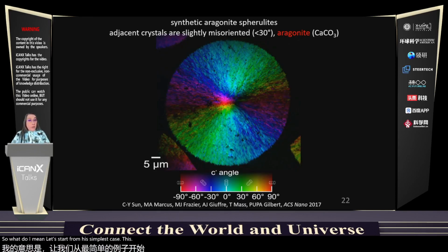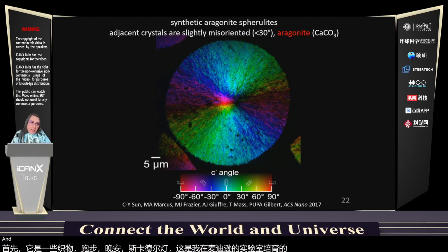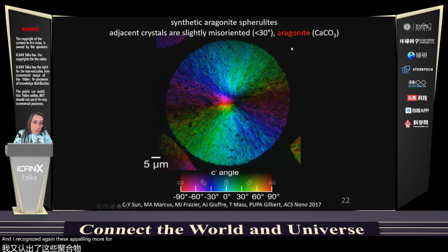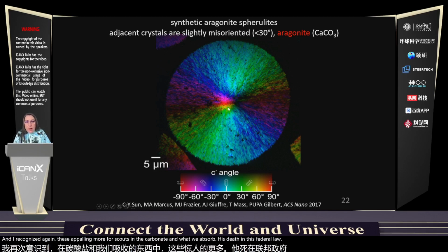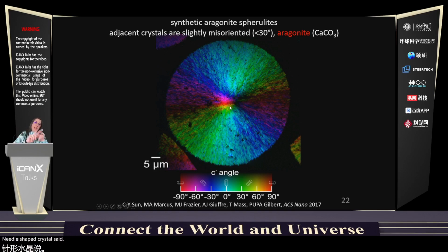This is a spherulite. It's actually not a biomineral one. It's a synthetic aragonite spherulite that was grown in my lab. And aragonite, again, is a polymorph of calcium carbonate. And what we observe is that in this spherulite, we have acicular crystals. It means needle-shaped crystals that, just like the radii of a sphere, start at the center and radiate away from it.